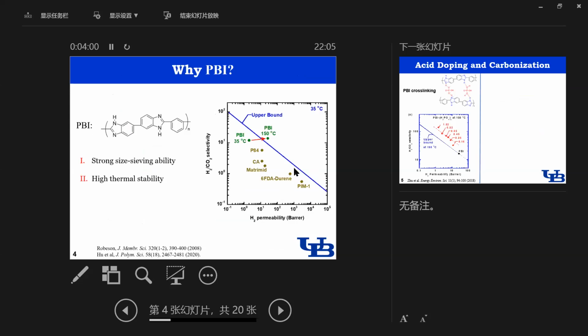So why do we choose PBI? Firstly, PBI contains lots of intermolecular hydrogen bonding, and this causes tight packing of the PBI structure and provides it strong size-sieving ability. Compared to other glassy polymers like PIMs, polyimides, or CA, PBI has higher hydrogen CO2 selectivity, above 10. Another thing, as the PBI structure is really rigid, its glass transition temperature is above 400 degrees C, which means gas separation can operate at high temperature, and we really benefit from high temperature gas separation. For example, hydrogen permeability of PBI can increase from 35 to 150 degrees C with no decrease in hydrogen CO2 selectivity.